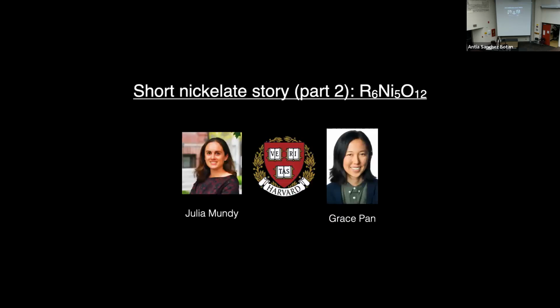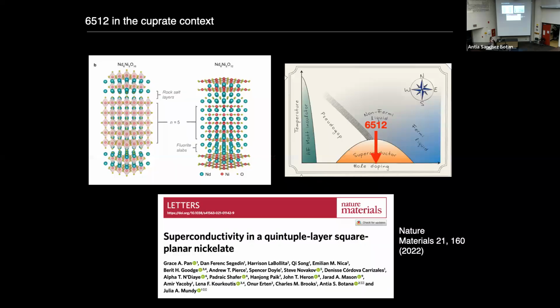So that takes me then into the second part of the story that I wanted to tell you about today, and that's the story of the 5-layer nickelates or 6,5,12 compounds that we have been looking at in collaboration with Julia Mundy. So remember that the 6,5,12 or 5-layer nickelate falls directly at optimal doping, where again, if this naive one-to-one analogy to the cuprates were to work, you would expect to find a superconductor. And as I mentioned in the beginning, that's indeed what we have recently found.